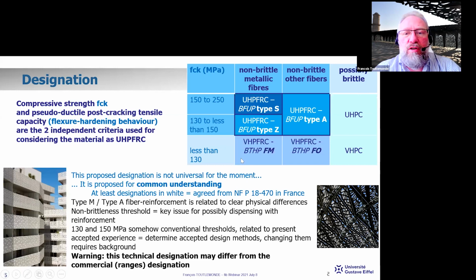The vertical axis in this diagram is compressive strength, and the horizontal axis is the pseudo-ductile post-cracking tensile capacity, so the hardening behavior in bending, which is obtained by a sufficient fiber content. These are two independent criteria that are used for considering the material as UHPFRC.